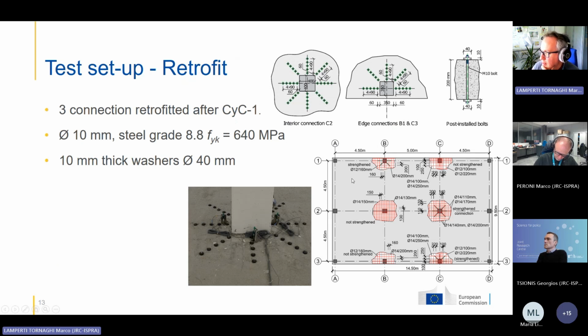After a first phase of tests, we simulated the earthquake on the full-scale building. We damaged some connections, and for three connections, B1, C2, and C3, we introduced the retrofitting after cyclic test 1, where the slab was not previously reinforced by internal reinforcement. We also tested a slab without punching shear reinforcement, damaged by the earthquake and retrofitted after the earthquake, to assess the possibility of strengthening a real existing building not designed for this purpose.